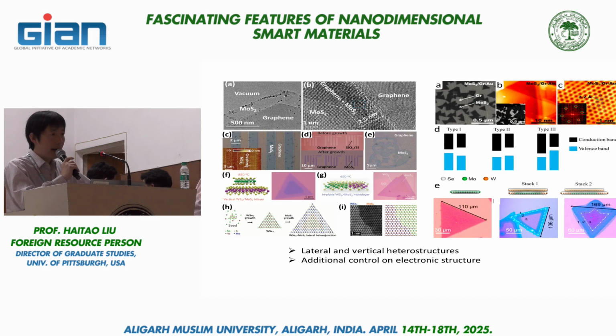They are not entirely single layer. If you look at the layer thickness distribution, they go anywhere from 1 layer to about 10, 12 layers. But you can get a lot of material. If you're interested in coating, energy storage, catalysis, this is the way to go.